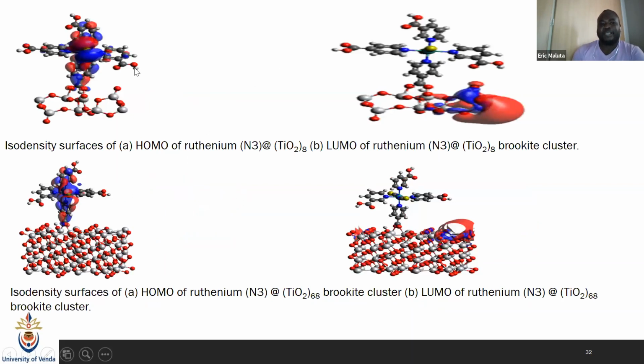Then we can see that the HOMO here is on the dye, and the LUMO goes to the Ti elements. Even here it can be seen that the HOMO is on the dye and the LUMO is on the Ti element. Like what I was saying, we really want to have more occupation on the dye so that there will be more electrons injected to the TiO2 when we are really working on the principle of the solar cells, and that will improve the efficiency of the solar cells.